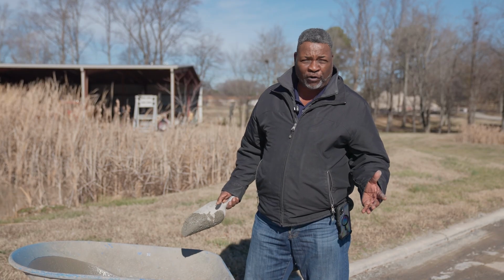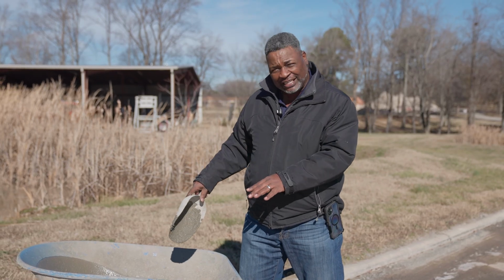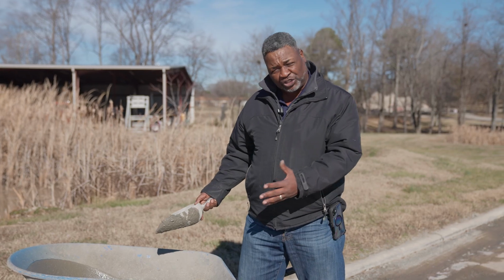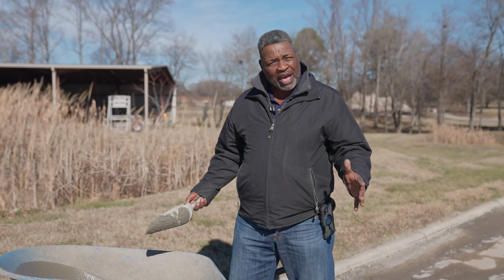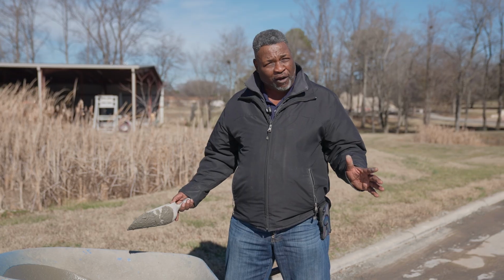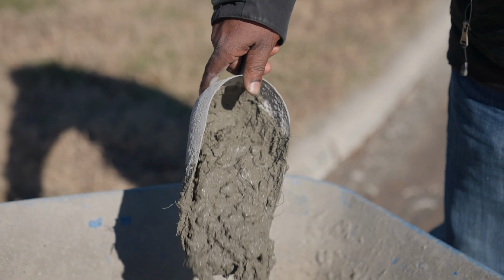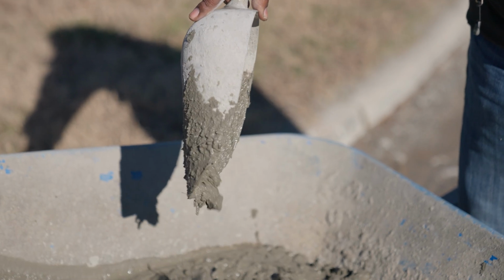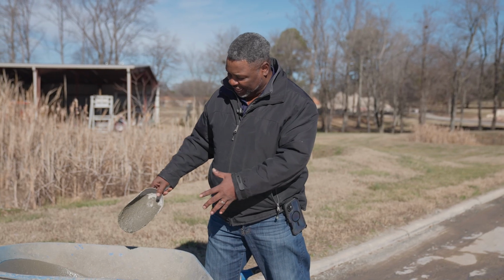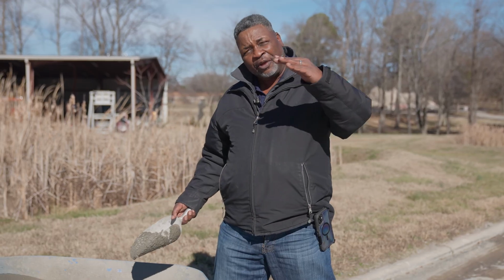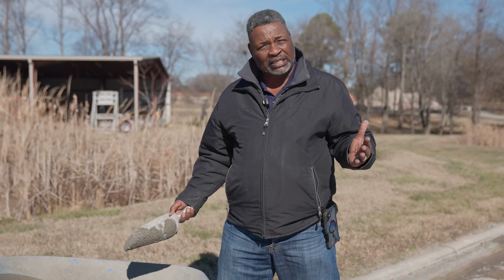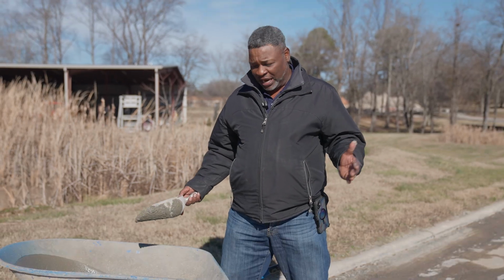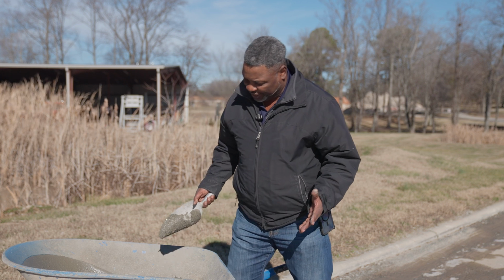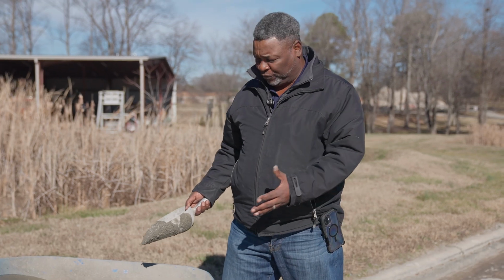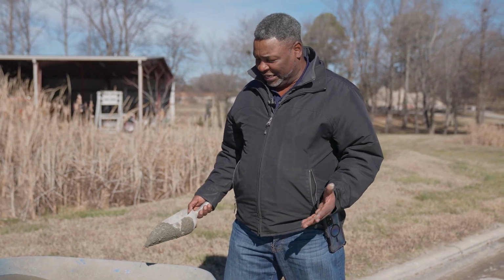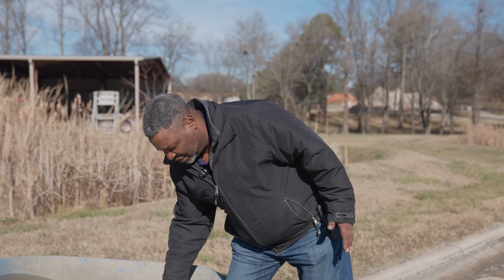One of the properties that we check for, folks, is the air content. If it's exterior concrete, we gotta entrain air in it to make sure that we don't have any issues when we get cold weather or freeze-thaw. We also have to check it for slump. How wet, what's the flowability of the concrete itself? I've been doing this for a minute, so I can tell you, looking at this, we probably got about a 5-inch slump. The higher the number, the wetter the concrete. The lower the number, the drier the concrete. I'm gonna call this a 5. We have a slump cone test that we do to perform that, but I've been doing this for a long time. I can tell you, that's a 5-inch slump. This is actually good mud.